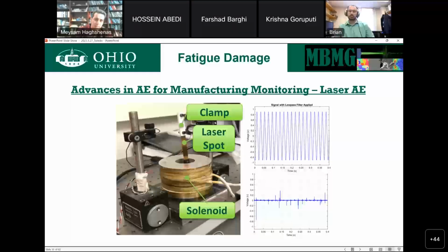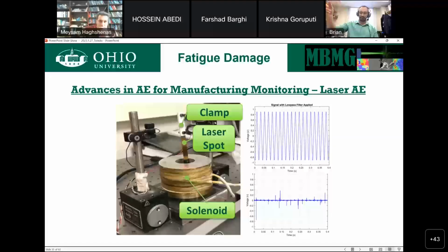The major limitation on acoustic emission comes from the fact we don't actually know the source. So these sources are happening, and what's happening is you have a damage initiate, which releases energy that's going to get convoluted as it travels through the material, convoluted with the sensor itself. So what you're actually getting as a wave is not the source. It's the source plus all of these other things. So you have to find a way to back that out, which means to get useful information out of AE, it's really difficult to just stick something on there and get a result and be able to say that's what that is.